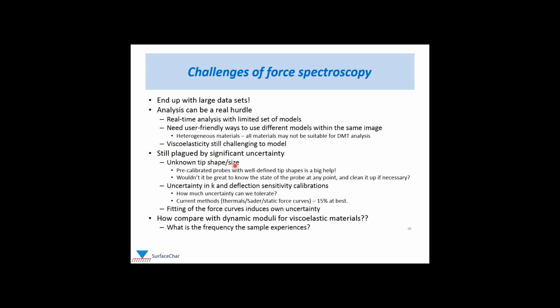That unknown tip shape and size is still quite the challenge for this measurement. Bede is going to talk about some pre-calibrated probes with well-defined tip shapes that are a big help to mitigate this issue. My dream or wish list is, wouldn't it be great to be able to get a snapshot, like an SEM image, of the state of our probe at any point, and then have a magic wand or something quick and easy to clean it up if necessary.